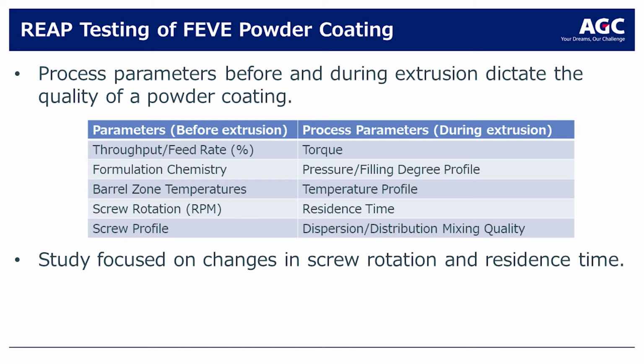In a powder coating, the ingredients of the paint are all solid. There are no solvents or liquids or anything. You're blending these materials together. You spray them on a charged metal substrate. They adhere to that, then you put them in an oven, and they cure when you put them in the oven. So it's a little bit different than a regular paint.